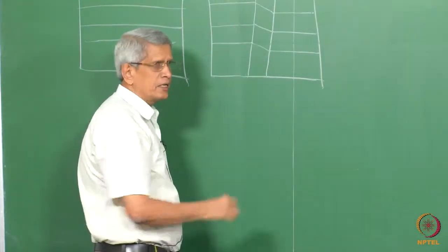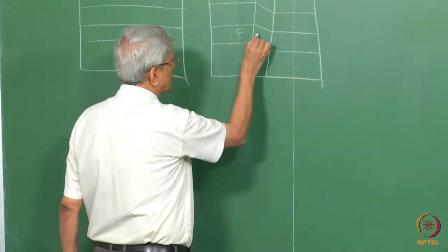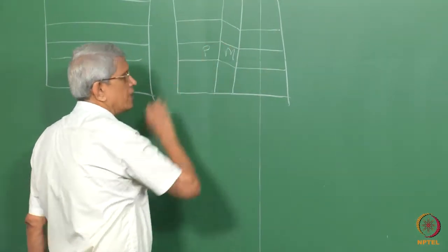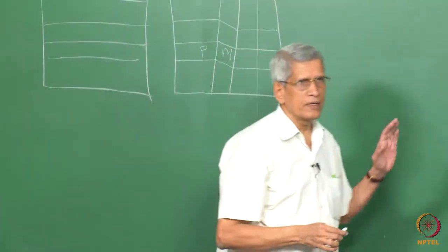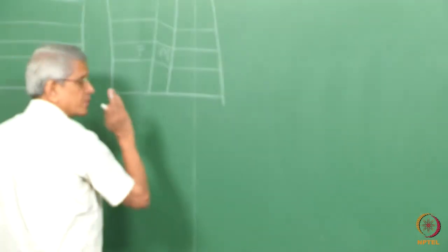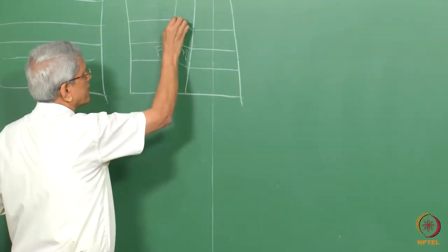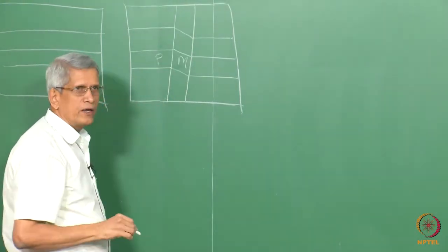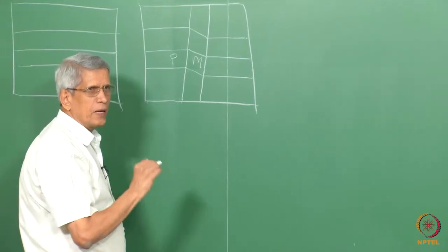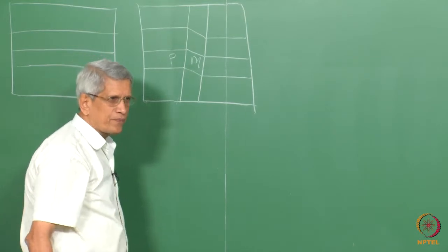Another aspect, if we look at it, is that till this interface, this line remains straight. That means that whatever the transformation which has occurred, the effect of the transformation is not there on the parent side. There are no strains being accommodated, and since the lines are continuous across the interface, this is an unrotated, undistorted plane, which we call the habit plane of the Martensite. These are all the observations which we have.